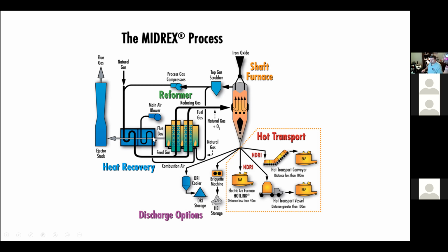The Midrex process, what they do is they have a proprietary reformer where you feed natural gas and it's going to basically crack that gas, produce hydrogen and CO, and that's fed into a shaft furnace, and the gas flows countercurrent to iron oxide pellets, which are fed at the top. And then the pellets progress down through the shaft and eventually get discharged.